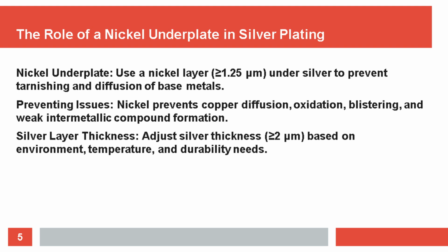To combat these issues, it is recommended to use a nickel underplate of at least 1.25 micrometers thick underneath the silver plating. A nickel underplate acts as a barrier, preventing copper or copper alloy elements from reaching the surface of the silver. Without this barrier, copper can diffuse through the silver, especially at high temperatures, leading to oxidation and tarnishing. This process can cause the formation of a tarnish film that changes the properties of the silver surface.